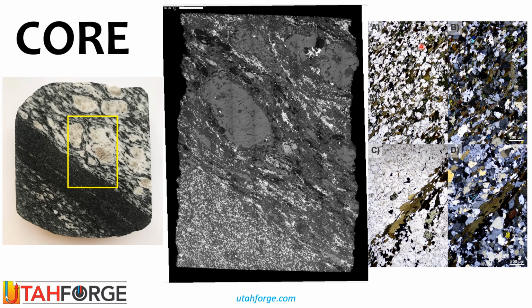At right are photomicrographs of the thin section in plane and cross-polarized light. You can see there's quite a bit of texture here that's the result of ductile plastic deformation under strain at high temperatures. Augens are these eye-shaped features. They are white and pink potassium feldspars in the core slab photo and are the large gray blocks in the middle SEM image. And a fine-grained mylonite, the dark band in the core photo, which has a lot of biotite in it.